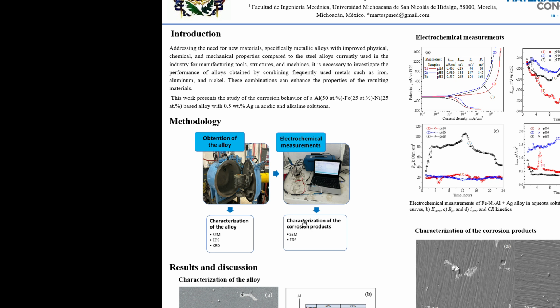Additionally, after the electrochemical test, the surface of the corroded specimen from the linear polarization resistance assessment was analyzed by scanning electron microscopy and energy X-ray dispersion spectroscopy to characterize corrosion products formation.